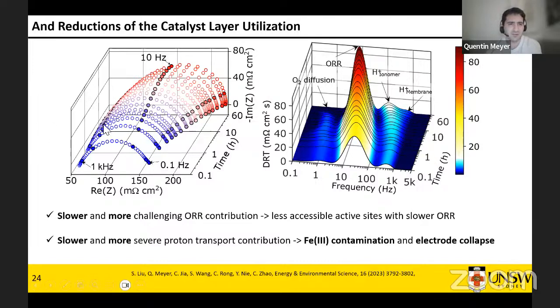The important thing here is that this is at the beginning of life. We got quite a small Nyquist plot. The point around 10 Hertz is towards the bottom. And as we degrade the cell, there is quite a large change, much, much higher resistance. And also the point at a frequency around 10 Hertz is moving closer and closer to the middle of the semicircle. And that tells us right away the reaction is becoming slower.